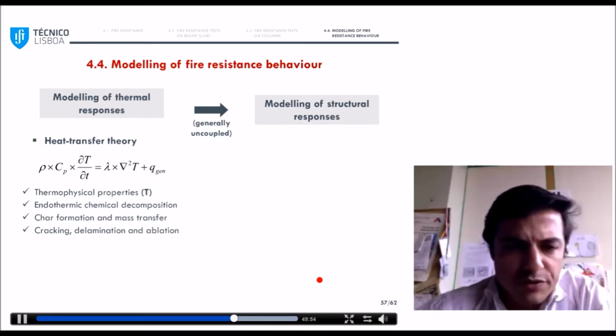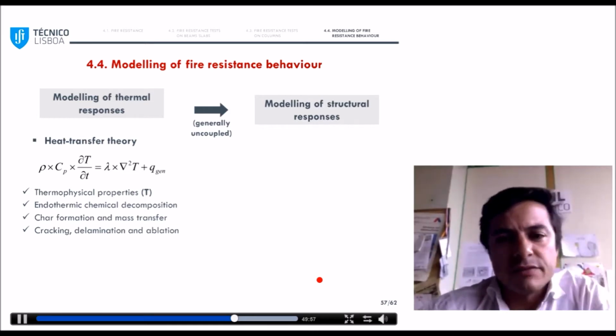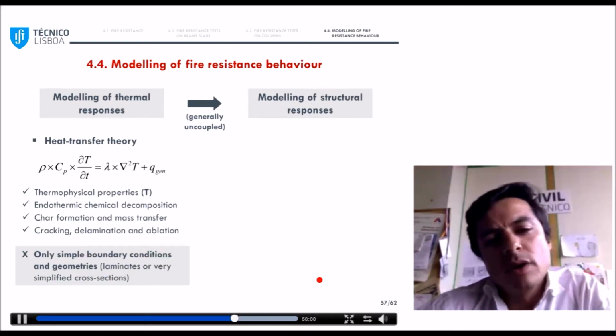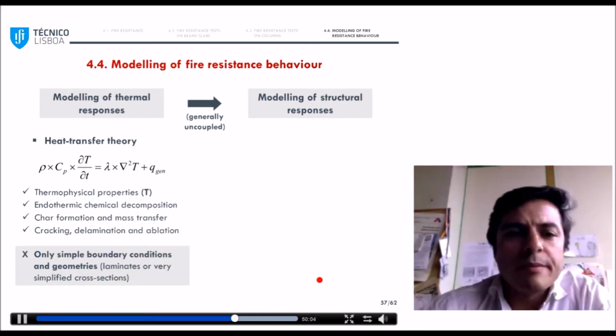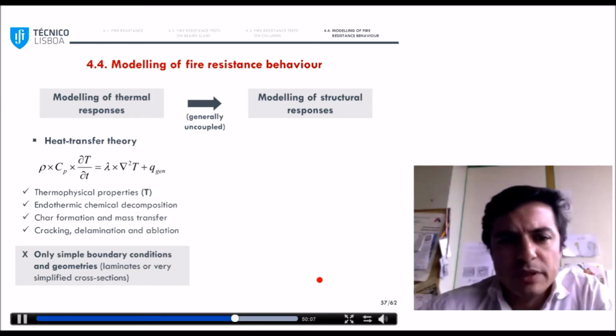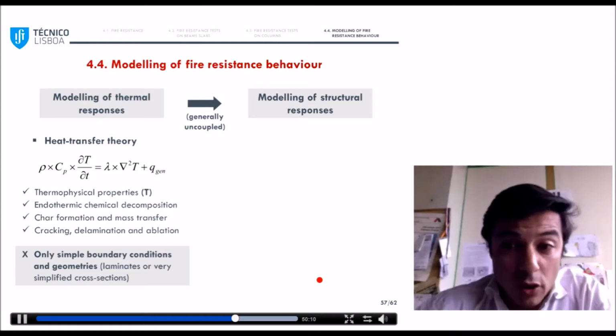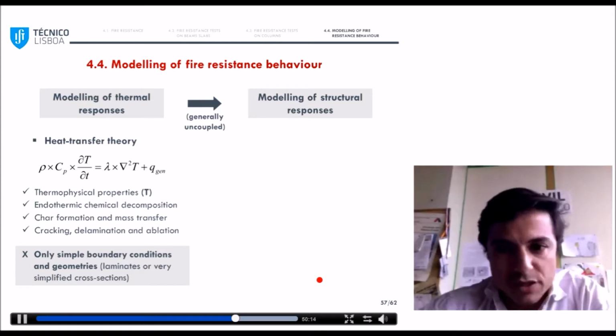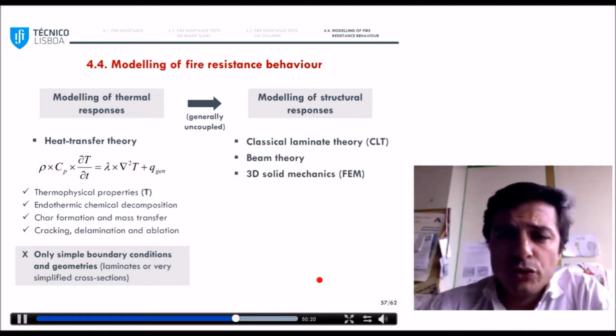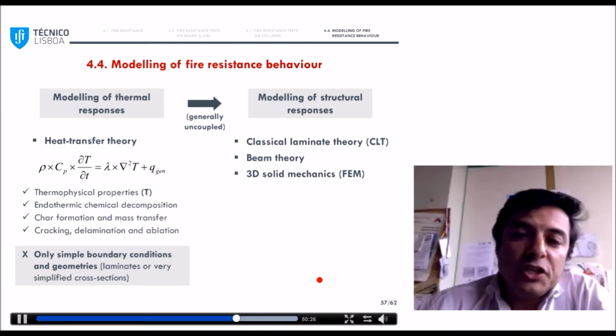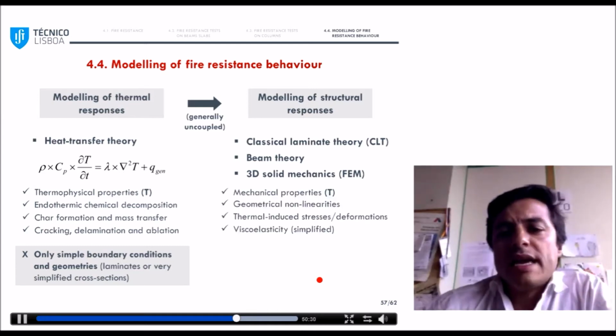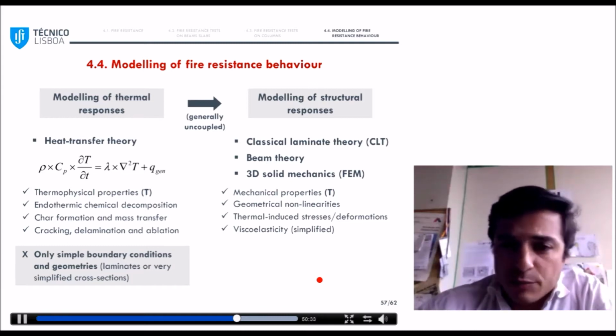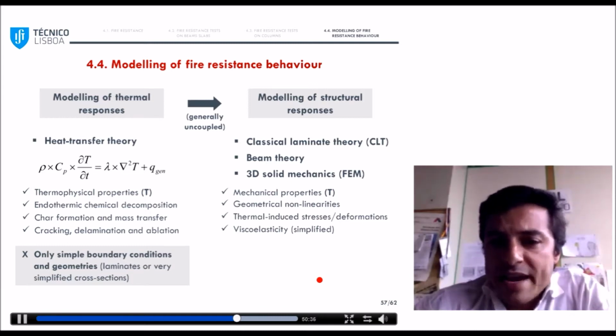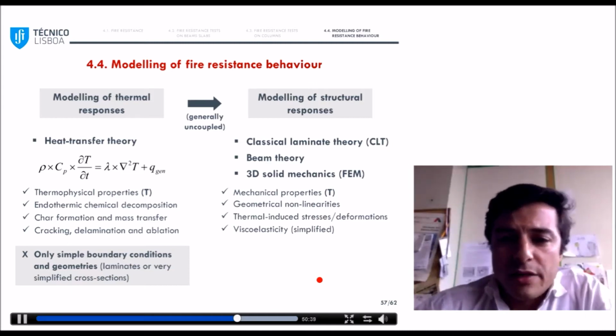So previous works in this field have very different levels of complexity, but one aspect that is transverse to all of them is that they in general consider quite simple boundary conditions or geometries, generally laminates or very simplified cross-sections. For the structural responses, different approaches have been pursued depending on the geometry of the problem. And again, different features were incorporated in the models, namely the temperature dependence of mechanical properties, the effects of geometrical nonlinearities, and the effects of thermal deformations and creep.